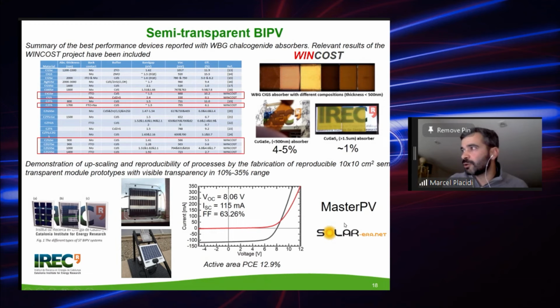Also, we work in another project, in the Master PV project, which is from the Solar-Era.Net call. We work on other ways of getting transparency, this time not by tuning the bandgap, but more or less using the same strategy followed by silicon, which consists of having transparent areas separating the different cells, as we can see there. So this is a CIGS mini module we fabricated in collaboration with a group in Halle in Germany. And we got from this module an efficiency close to 13%. With this one, I think it was around 20% transparency in the visible range. So this is a very good result, and currently it is under monitoring on the rooftop of IREC.